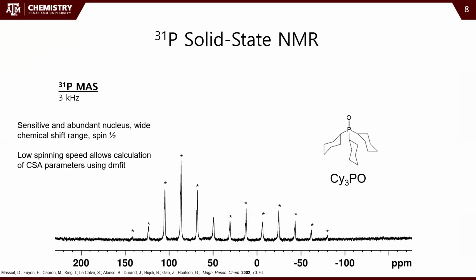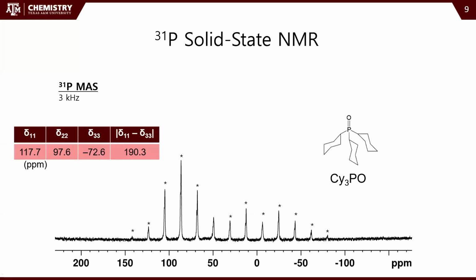Starting with just the phosphine oxides, you can see that the chemical shift anisotropy is pretty wide. And the reason for that is that the chemical shift anisotropy comes from the dipole, the anisotropy around the shielding of the phosphorus nucleus, right? So if you have a big dipole from the phosphorus to the oxygen, the shielding's less symmetric, and so you'll have a larger chemical shift anisotropy. So I calculated all of the CSA parameters using DMFit. And yeah, you can see a span of about 190 ppm, and then all of the delta 1,1, 2,2, and